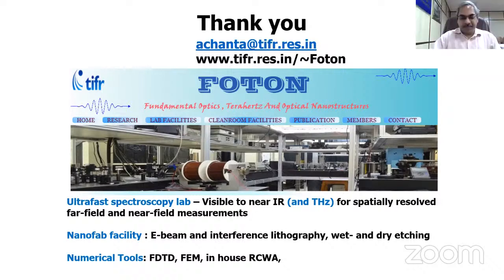Right. The simplest thing I started with, before our clean room was even built in TIFR, was to use two laser beams and make them interfere. You get dark and bright fringes, so you can get a one-dimensional grating, a periodic structure. If you do partial exposure and then rotate your sample, you can get a two-dimensional pattern. There can be circles, there can be squares, depending on the exposures. You can actually manipulate these things. This doesn't require very high-end equipment.